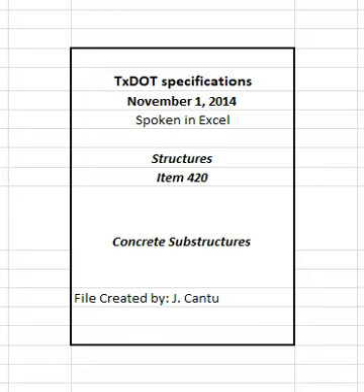Deposit concrete in water only when shown on the plans or with approval. Make forms or cofferdams tight enough to prevent any water current passing through the space in which the concrete is being deposited. Do not pump water during the concrete placing or until the concrete has set for at least 36 hours. Place the concrete with a tremie or pump, or use another approved method, and do not allow it to fall freely through the water or disturb it after it is placed.